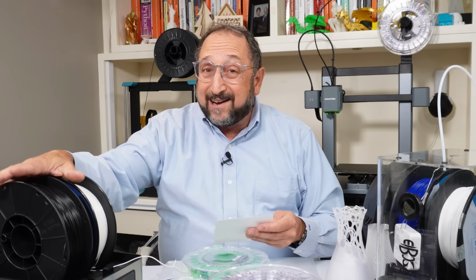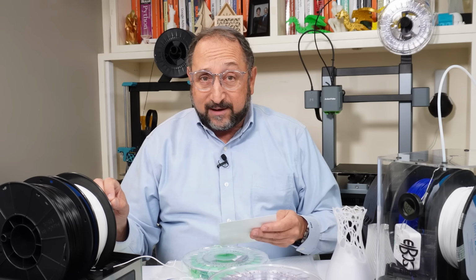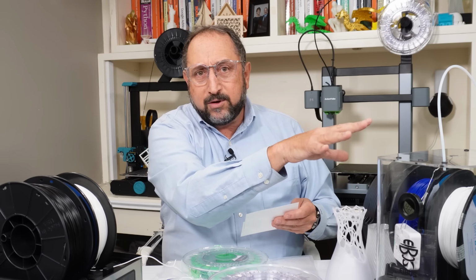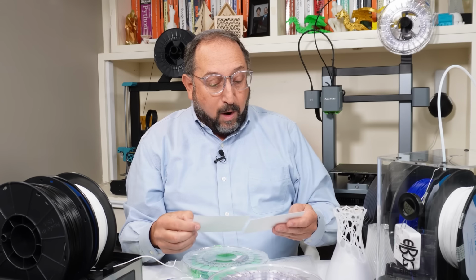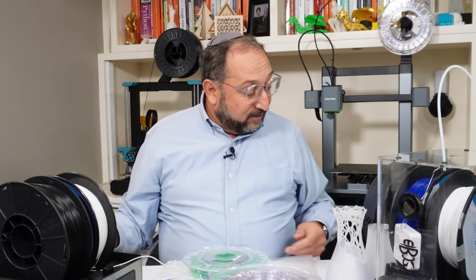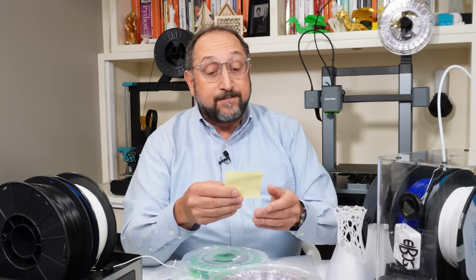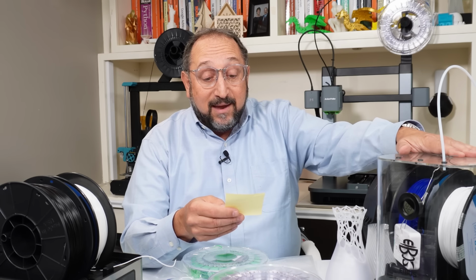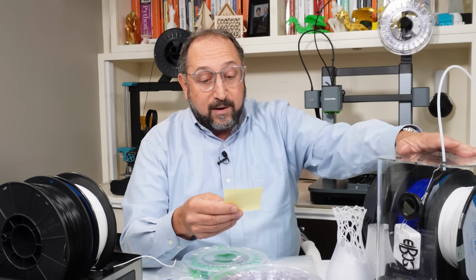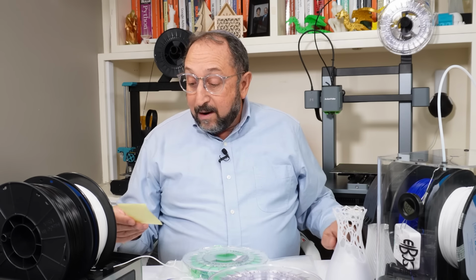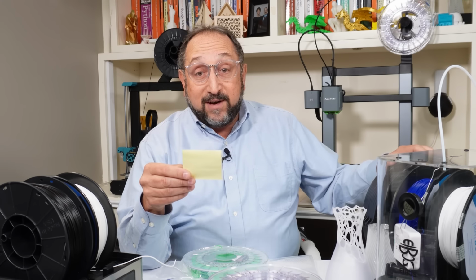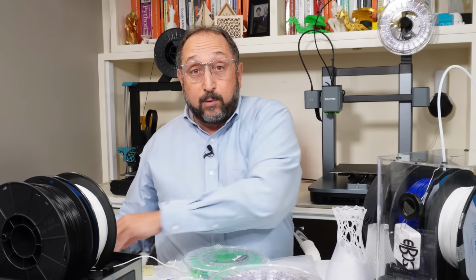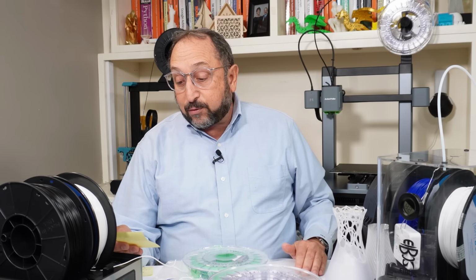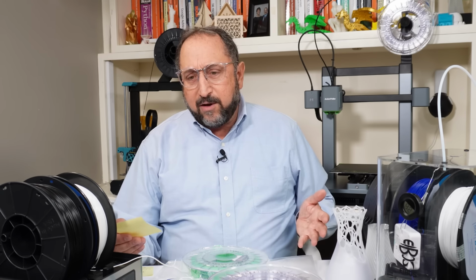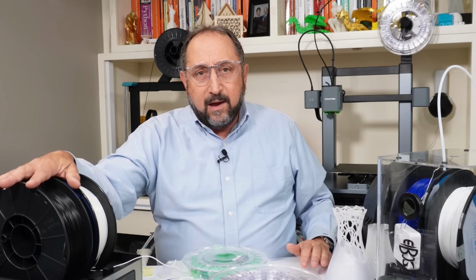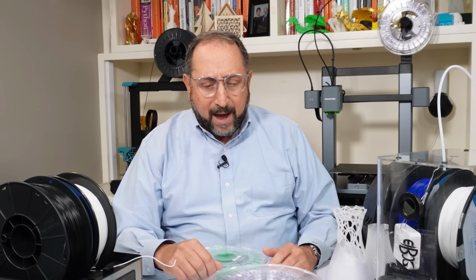The Fixdry ran a little cooler than the set temperature. The Eibos ran hotter, which is more problematic. The Sunlu was the closest to the actual set temperature. In terms of price, the current model of the Eibos dual reel filament dryer is $120. The Sunlu was $70 for a single reel. They do make a double reel model. And the Fixdry was really a good value at $93 for a dual filament reel model.